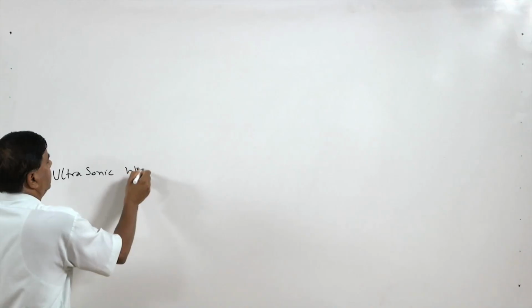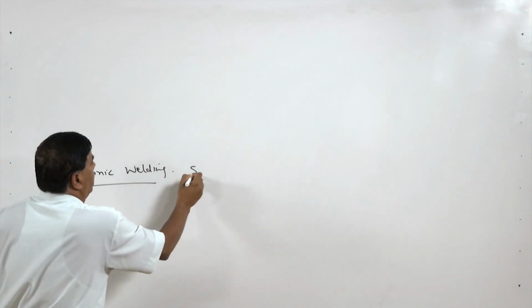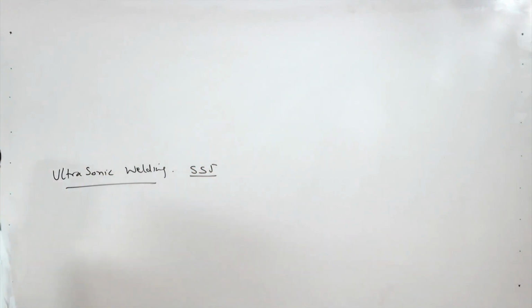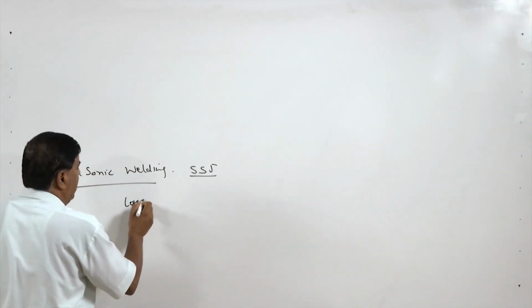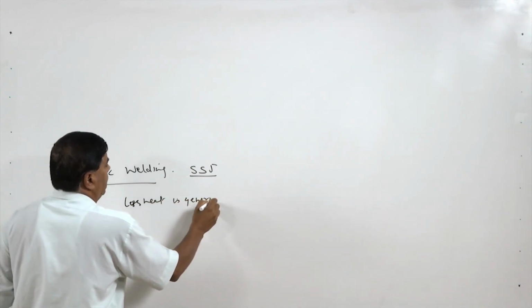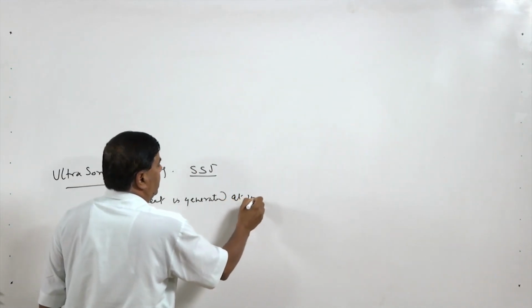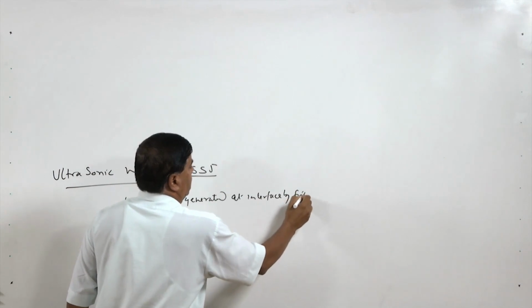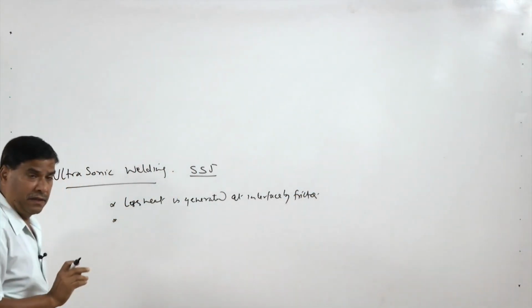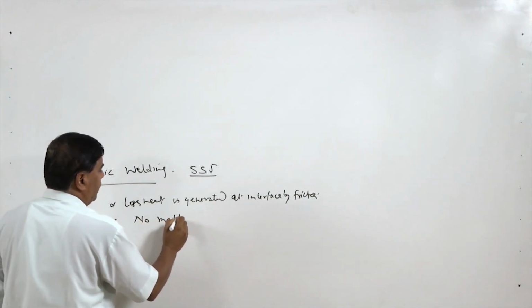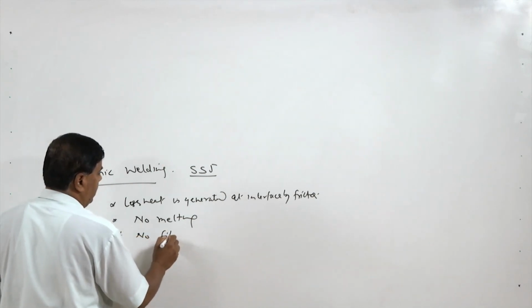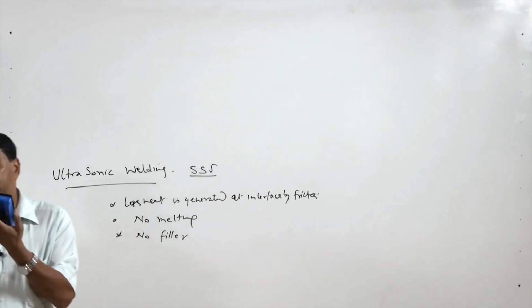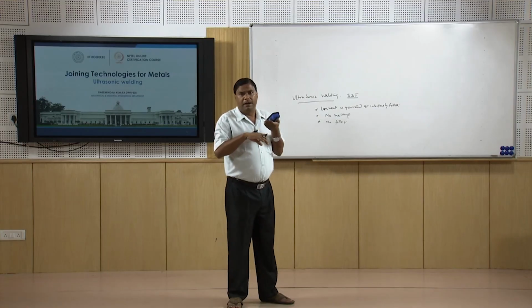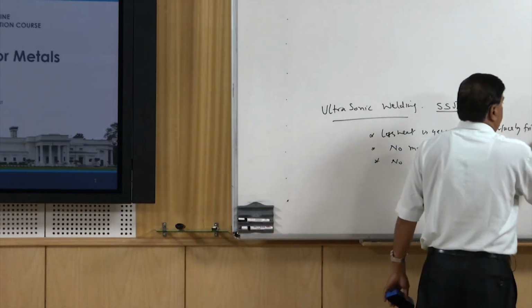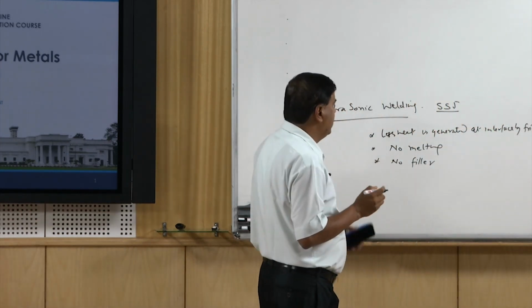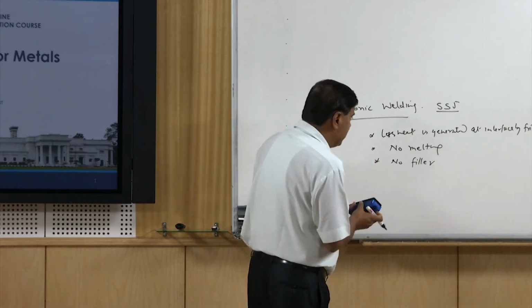This ultrasonic welding process is one of the solid state joining processes, where very little heat is generated at the interface by friction. Another important thing: there is no melting or fusion, and no use of filler. The mating surfaces are brought together in metal to metal contact, and then using ultrasonic vibratory energy, the joint is made through localized plastic deformation at the interface.